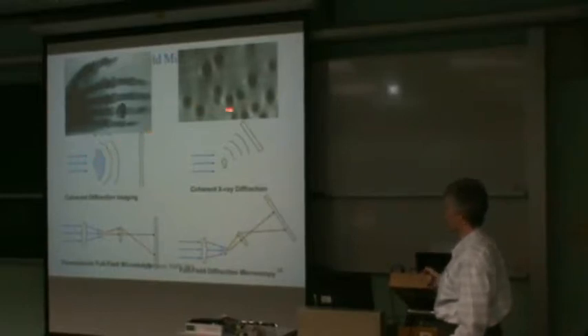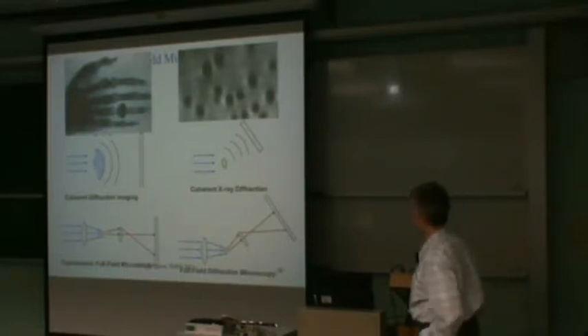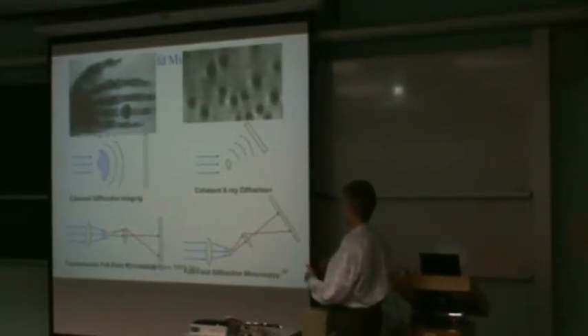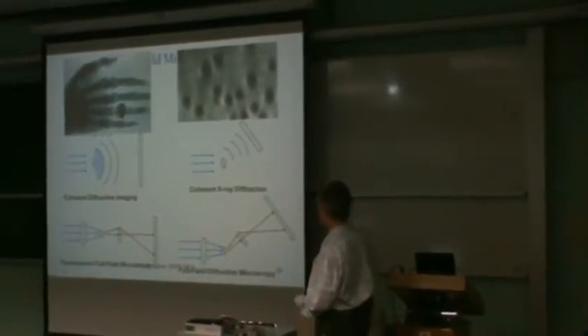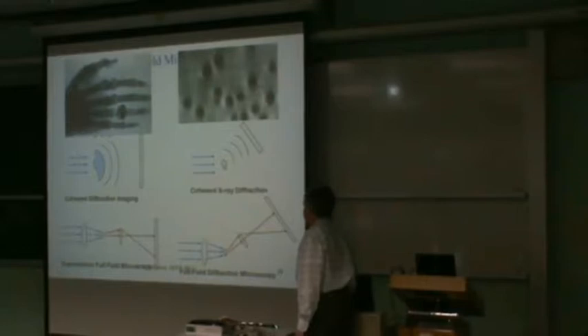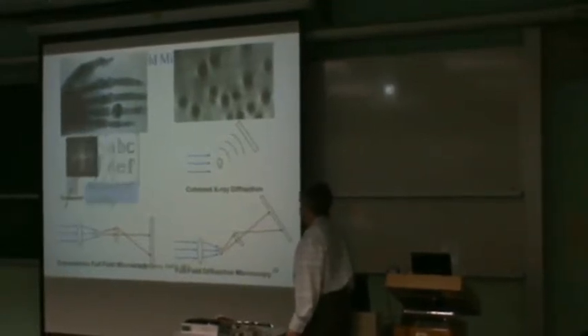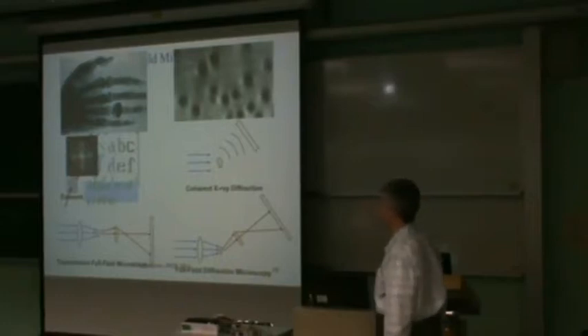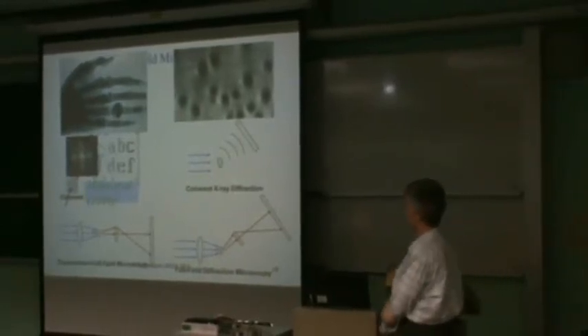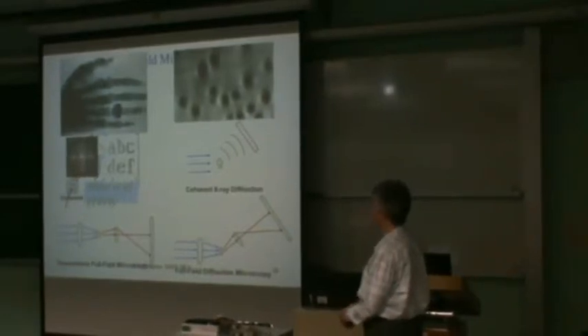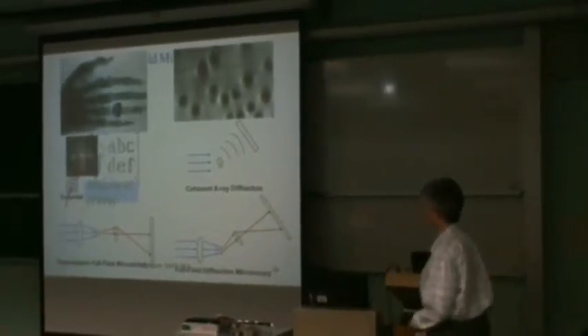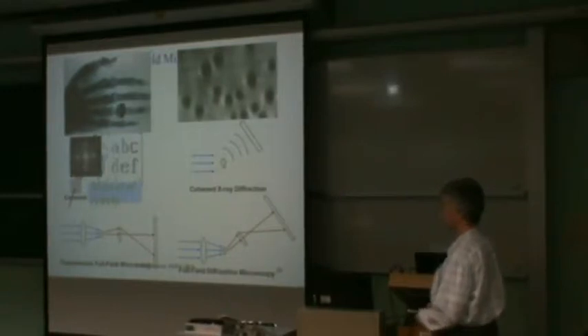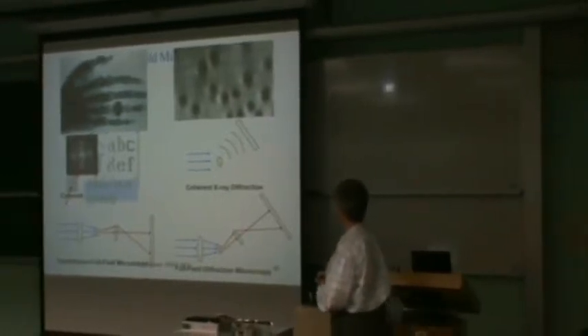Okay, so the second method that you can use is to measure, you shine the X-rays onto the sample, and instead of measuring just what comes straight through, you measure the diffraction pattern that comes out of the other side. And this diffraction pattern can be inverted by using the fact that it can be measured more finely than the fringe spacing of the diffraction pattern. And the famous example that really opened up this whole field of diffraction imaging is the one of Jianwei Miao that was published in 1999. So it's very much a 21st century technique that is becoming available. And this one, unlike the first method, requires the coherence of the source in order for it to work.